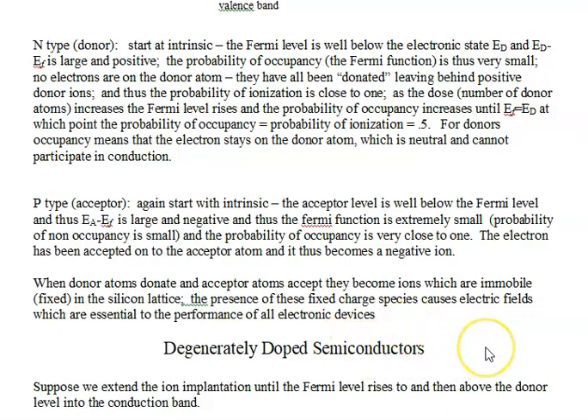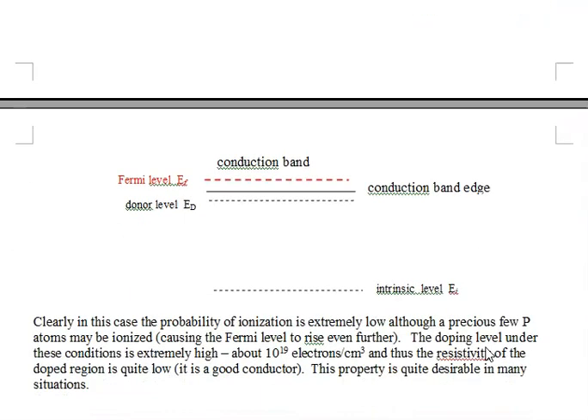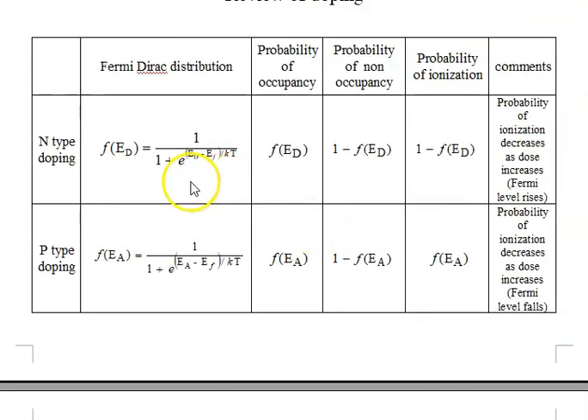Okay, degenerately doped semiconductors. So what is that all about? Well, what it's about is the following. Consider, for example, N-doped. For an N-doped, the Fermi level rises as the dosage increases. It just keeps rising and rising. We keep banging in phosphorus atoms into the lattice until we arrive at the donor level E sub D. And at this point right here, we see that ED minus EF is 0. So this becomes a 1, 1 divided by 1 plus 1, or 1 divided by 2. So the probability of ionization, or the probability of occupancy, same thing, is 1/2.